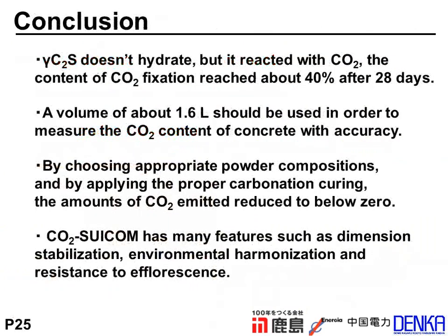The conclusion is below. The gamma C2S does not hydrate, but it reacts with carbon dioxide. The carbon dioxide fixation content reached about 40% after 28 days. A volume of about 1.6 liters should be used in order to measure the carbon dioxide content of concrete with good accuracy. By choosing an appropriate powder composition and by applying the proper carbonation curing, the amount of carbon dioxide emitted is reduced below zero. Finally, CO2-SUICOM has many features such as dimensional stabilization, environmental harmonization, and resistance to efflorescence.